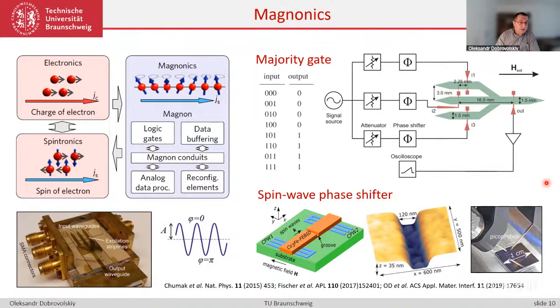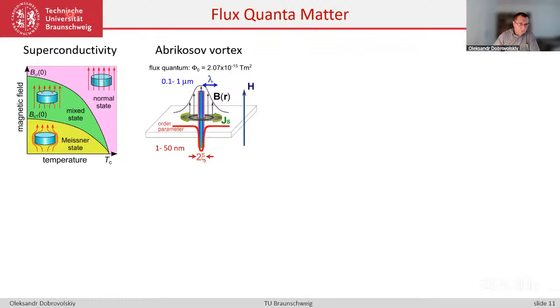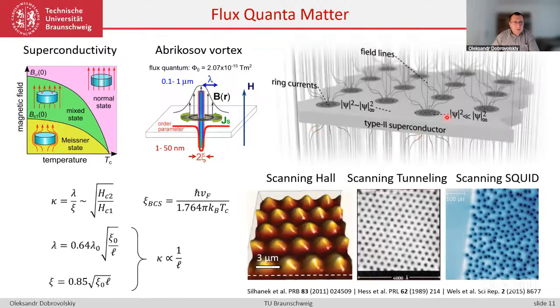what is particularly interesting in relation to magnonics if we have a superconducting film close to it. Most of the technologically relevant superconductors are known to be of type 2. So in the phase diagram, there is a region where they are penetrated by vortices, the mixed state. Just to remind what a vortex is: a vortex can be viewed as a whirl of current surrounding the normally conducting core where the order parameter falls down to 0. The magnetic field is at maximum at the vortex core and attenuates over a length scale given by the magnetic penetration depth. A fluxon is one magnetic flux quantum carried by vortices in most conventional superconductors, and the repulsive interaction between vortices makes them arrange to form a vortex lattice, which is illustrated in this cartoon.